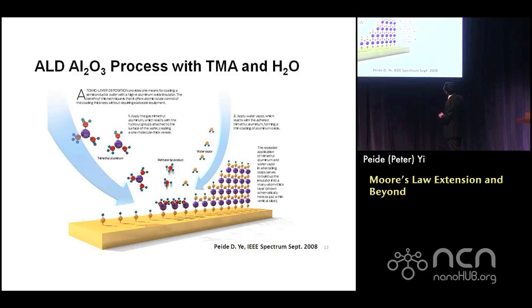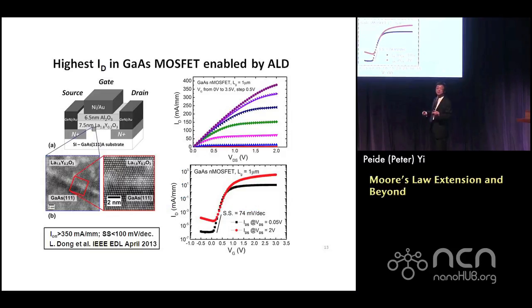Because it's a self-limiting process, it can be grown on 300 millimeter wafers everywhere, as accurately as an atomic layer. Really, the accuracy can go down to angstrom thickness. And over larger areas, as I mentioned, within 6-7 years this technique was commercialized and put into integrated circuits. All the high-K dielectric nowadays, using hafnium oxide, is made by this ALD technique.